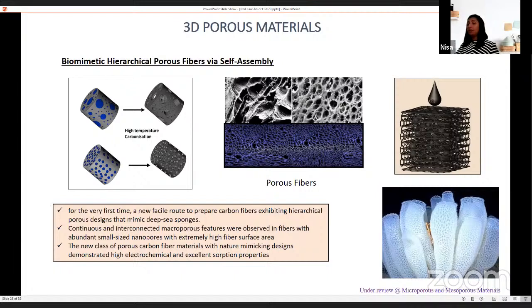So we have demonstrated this to make functional fibers. Here we designed marine sponge-like functional fibers. These fibers exhibited meso, micro, and macro-sized porous features, both on the surface and in the cross-section of the fibers. And these fibers exhibited high surface area. We also checked the adsorption and energy storage properties of these fibers.